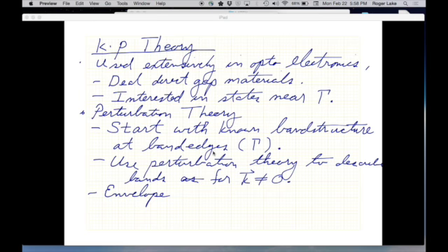And I guess there's really nothing wrong with that. But people used to get into heated arguments about things like you really can't take into account, in this theory, interfaces really well, because, say, an MBE grower can grow a quantum well or grow a crystal like gallium arsenide, for example. So the surface, if you're growing a quantum well, could terminate on the arsenic atom, or it could terminate on the gallium layer, because they grow in layers, gallium, arsenic, gallium, arsenic. And if you're doing an atomistic model, like we did in our localized orbital, then that's all automatically taken into account.